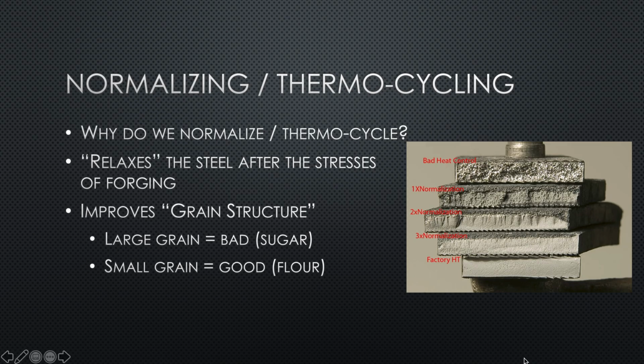You'll hear people say, oh, check out my grain structure, and they'll have a picture of a snapped blade. The picture on the right is a really good one that shows you the difference. The top one looks kind of like sugar, as opposed to the very bottom one that looks more like flour. The more normalizing, usually up to 3, the better. After 3, you're losing any benefit of doing a 4th or 5th. But if you normalize, you'll get a better grain structure, and this just means your blade is less likely to crack and to snap. Having a very coarse or large grain structure means your blade is inherently weaker because those crystal bonds are not as tight.